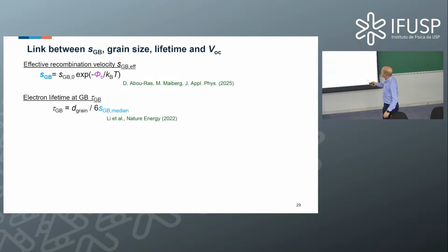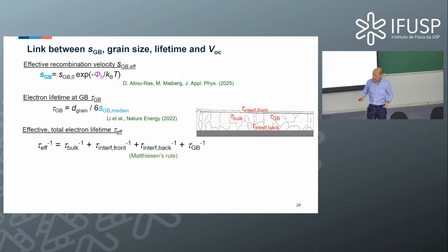So how can we proceed? We know that we can describe the effective lifetime as a contribution of the lifetime in the bulk. And if we now have a complete device, we have a bulk lifetime, we have a grain boundary lifetime, but we have, of course, also lifetime at the interfaces. And we can sum the inverses of these lifetimes up to get the inverse of the effective lifetime. That's quite convenient.